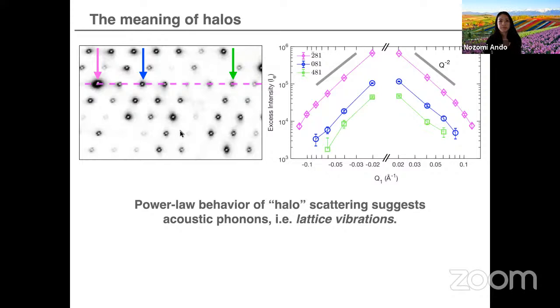Well, here I'm showing a zoom in of a slice of reciprocal space. And if you choose a few very strong, roughly symmetric halos and look at how the intensities decay away from the Bragg peak positions, which are already filtered, that's why they're white in the middle, then we see that there's a characteristic power-law decay with an exponent of 2. And that type of decay is suggestive of so-called acoustic phonons or lattice vibrations. And if you plot the intensity on a log-log plot, you could see that this region is quite linear all the way to very close to the Bragg peaks.